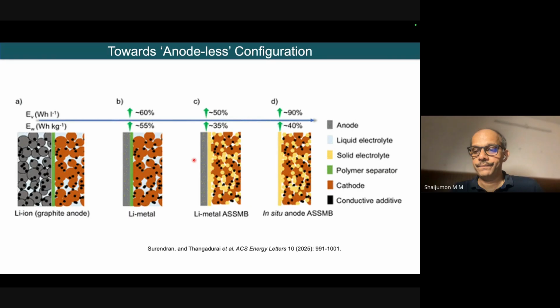It is important in the sense that, from a traditional lithium-ion concept where you have a liquid electrolyte, if I remove the graphite and place a lithium metal there, it is called a lithium metal battery. You see the increase in the energy density: volumetric is upper and the gravimetric is here. There is a huge increase in the volumetric energy density when I come to this kind of anodeless battery. That's exactly what I was telling about. An anode is formed in situ here to bring this all solid state metal battery. You gain quite a lot in terms of performance, especially the energy density. And the moment you have higher energy density, these are much more useful for vehicular applications.